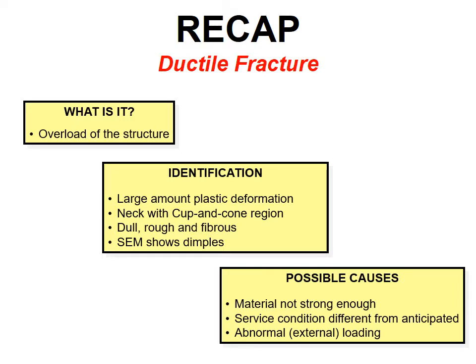Before we end on ductile fracture, let's do a quick recap. Firstly, it is important that we know that ductile failure is due to the overloading of a structure or the application of a force exceeding that of the metal's yield strength. Secondly, we have to be able to identify or differentiate it from the other failure or fracture modes. Ductile failure can be identified by its characteristics of having 1. Large amount of plastic deformation. 2. A neck with a cup cone region. 3. Its fracture surface looking dull, rough, and fibrous. And lastly, SEM images will show dimples in fractography study.